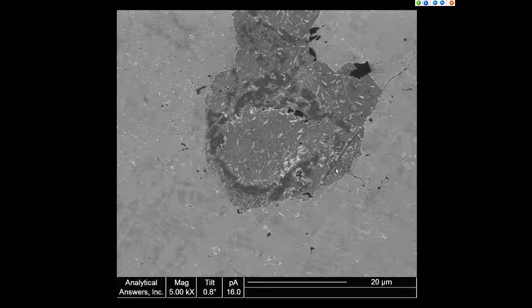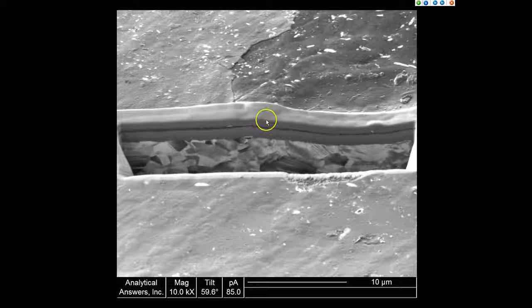So when we do the cross-section through this in the same way we showed earlier, we can tilt the sample and see very clearly that the actual dimple was present in the substrate initially, and that the platings just wrap right around the defect. And so the defect, while not good to have in the sample, is not terrible because at least the substrate is coated over with the protective platings. And again, we see a very thin layer of gold on top of a nickel layer in this case. And so that gives us our protection, and we can verify that the sample will still function properly.